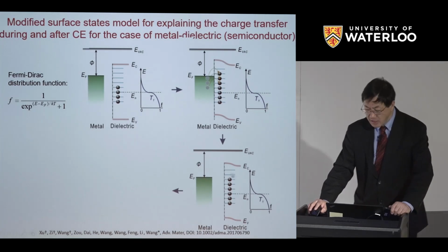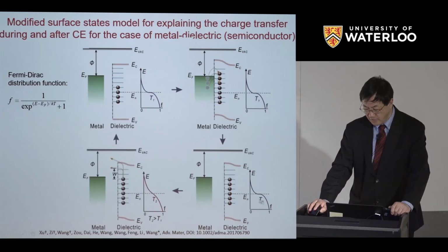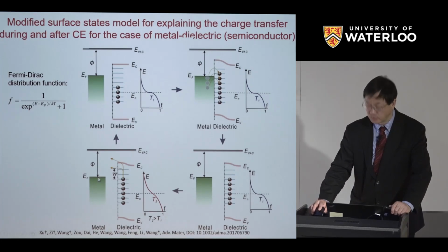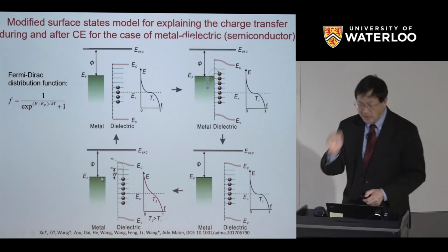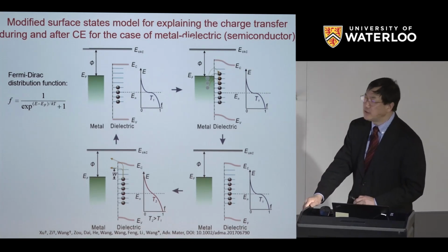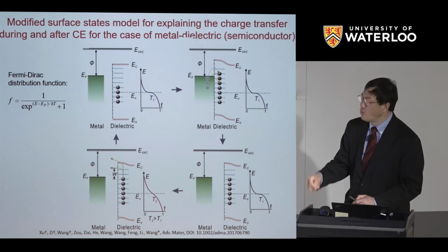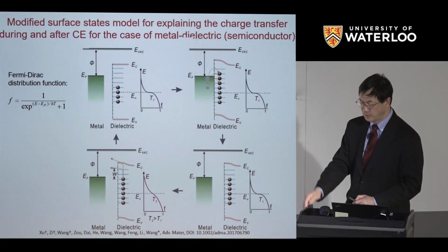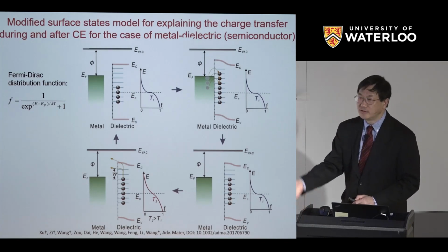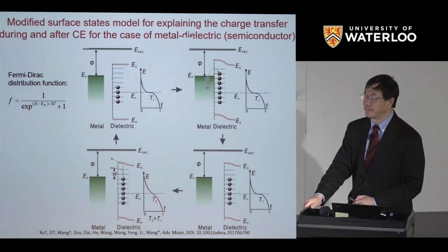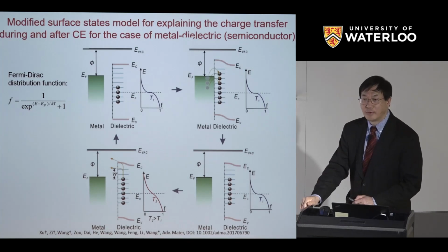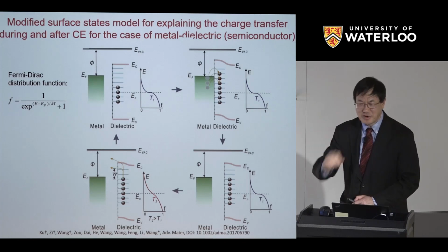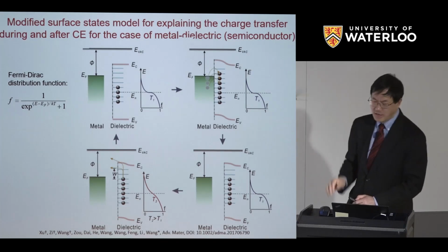Then if you heat up to a higher temperature, let's say from T1 to T2, the Fermi-Dirac tail goes up. So it means there's a possibility that this electron can hop out, with kT, overcome the barrier, and go to the other side. So this is for metal and semiconductor, which we can easily understand. However, in our life, everything has a triboelectric effect, like wood, amorphous materials, glass, whatever. This model cannot explain that because none of these have a well-defined band structure as we draw here, with surface states. So how do we understand that?